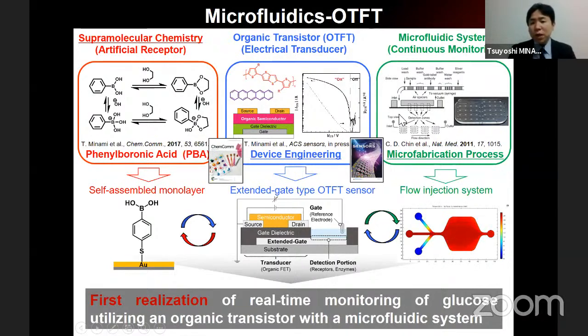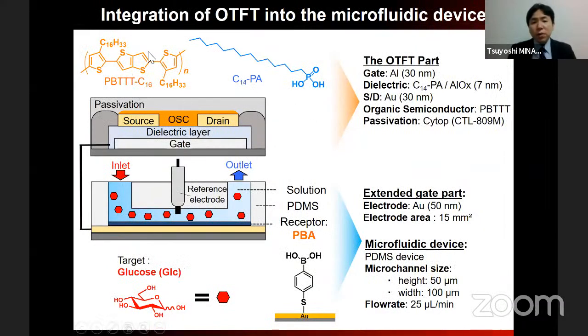And we also functionalize the gate electrode, with the microfluidic system on it. First, we tried to realize a microfluidic system attached to an extended-gate type organic transistor for glucose detection. So here is the design. As I said, we use a PBTTT unit for the semiconductor layer. And to decrease the operation voltage, we employ a gate dielectric material, tetradecylphosphonic acid. Because this is a very thin, molecular-level material, we can raise the dielectric value, so we can decrease the gate voltage. The surface of the gold electrode is functionalized with phenylboronic acid.